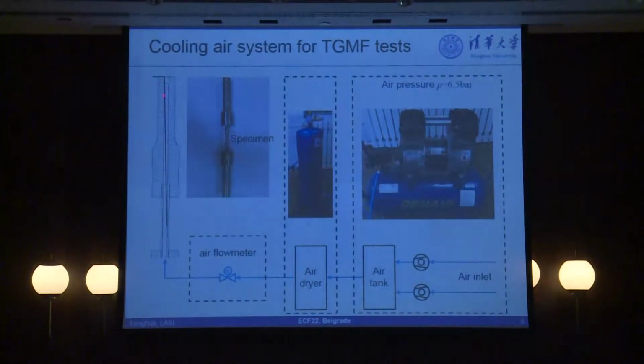Okay, but we need to measure the temperature on the inner surface, which becomes a very difficult task. We try to measure it, for instance, by bringing a thermocouple onto the surface and trying to measure the temperature here. For this specimen, we found the measured value is very sensitive to your pressure on the surface. Actually, the thermocouple measures the average temperature around the thermocouple. Therefore, the value you obtain is actually not the real material temperature, but the environmental temperature.